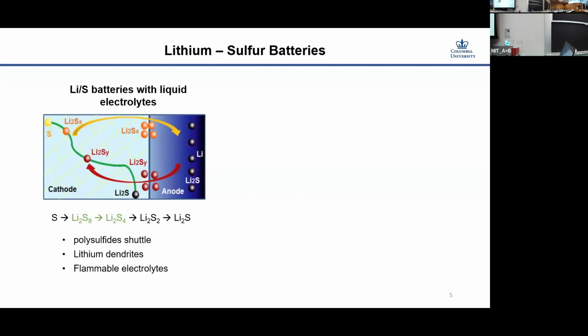Lithium sulfur batteries have been studied for a really long time. Although it's very attractive, there are some intrinsic problems that are very difficult to solve, especially with conventional liquid electrolyte. With conventional ether liquid electrolyte, the sulfur is first reduced to lithium polysulfides in the discharge process, which are soluble in the electrolyte. Such soluble polysulfides can diffuse to the negative electrode to have side reactions with the lithium metal, and this is called the shuttle effect. And this is very bad for the cycling performance of the lithium sulfur battery.